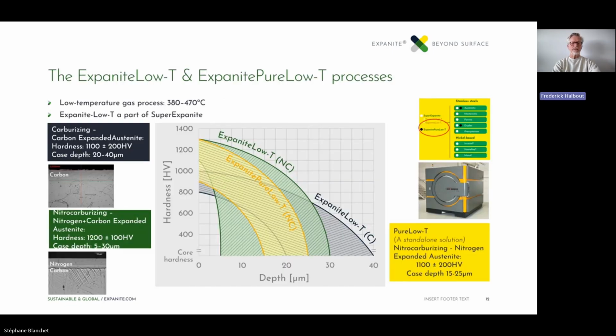If you go to the next slide, you can see the next process step that we are doing is called Expanite Low-T. That is conducted in an oxygen-free environment, not vacuum, however, at lower temperatures, around 450 degrees. It can vary, of course. And this is a nitrocarburizing process where we diffuse nitrogen and carbon into the surface. The diffusion depth here is very concentrated to the surface and has a diffusion depth of, as a standard, 20 microns. We can play around with those depths a little bit, from 10 to 30 microns, but it's not recommended to go over 30 microns due to the compressive stresses that build up in the surface. But 20 microns is more than enough in many applications.